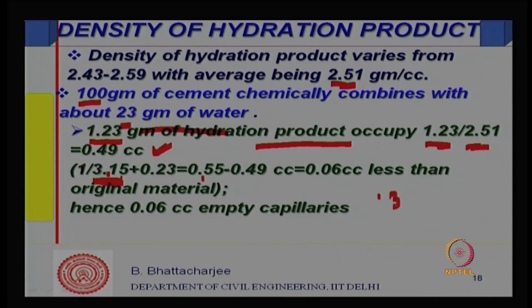So, 1/3.15 plus 0.23, since cement occupies that volume, sums up to 0.55, and the solid product of hydration occupies 0.49.